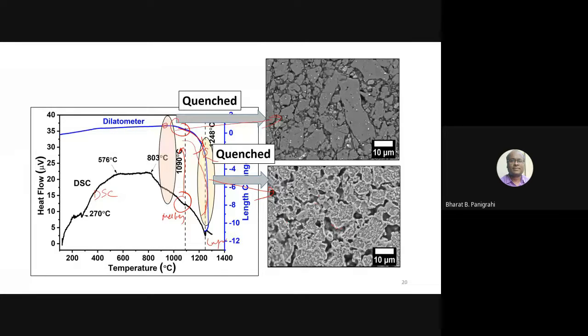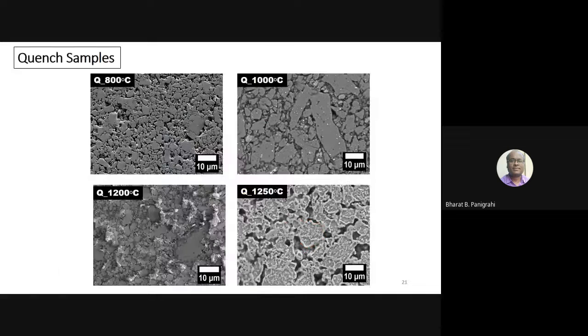When you quench it, it is frozen as it is, and you can see around the grains the liquid droplets that have frozen out on the surface. So the grains are wetted by whatever small portion of liquid is formed. You are actually able to capture the liquid phase here. It says that a liquid started forming at that particular temperature, and when you allow proper time, this leads to a massive densification.